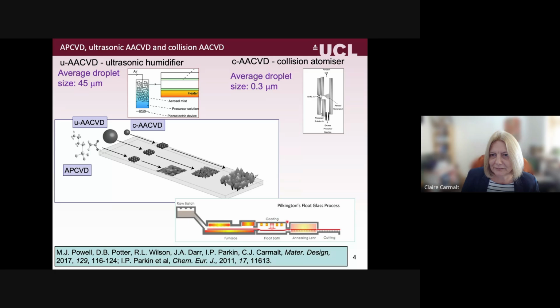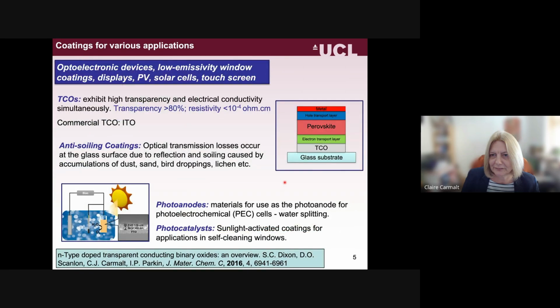And this just gives you an example of the Pilkington float glass process. As I mentioned, they tend to heat up to very high temperatures above 600 degrees, and it's in the float bath in this area here that the coating takes place using APCVD. So if we wanted to incorporate our AACVD, it would be in this area that you would have to incorporate the film growth. So let's have a look at some of the applications that we've been interested in.